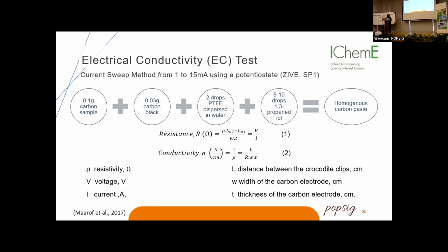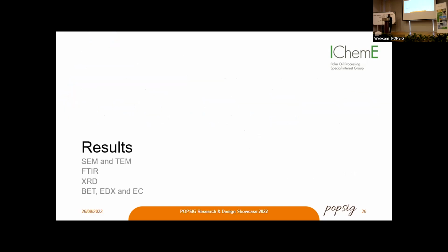The carbon electrode was formed by mixing carbon samples, carbon black, PTFE, and 1,3-propanediol to form a homogeneous paste before being shaped into an electrode and dried. So the conductivity was calculated using the equations shown. Moving forward to the results,